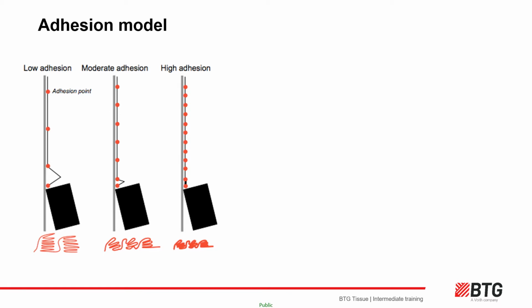These adhesion points are provided by the Yankee base chemical or adhesion aids and pulp extractables carried forward in the wet sheet. The more red dots, the more adhesion. This can be either from the coating chemical addition, as we've said, and the type, or from the hemicellulose containing pulps. The black rectangle represents a creping blade. The red folds or crepes below the black blade represent the crepe pattern achieved under each adhesion condition.